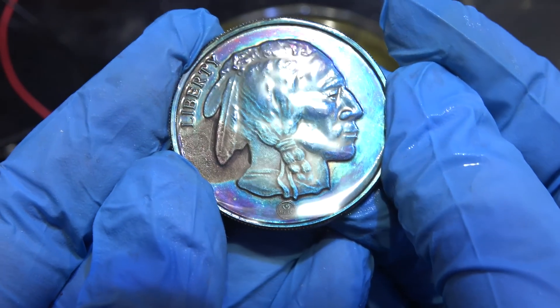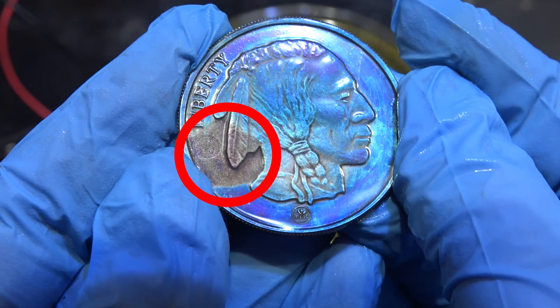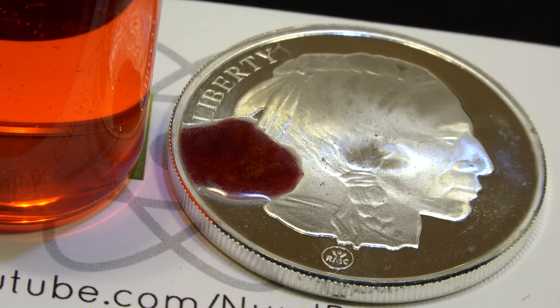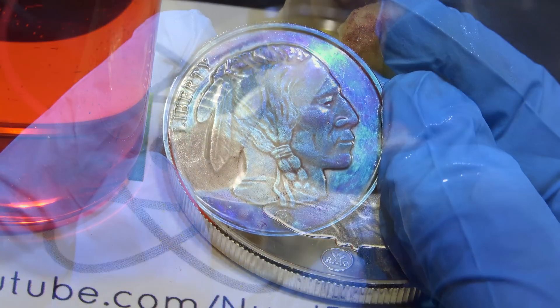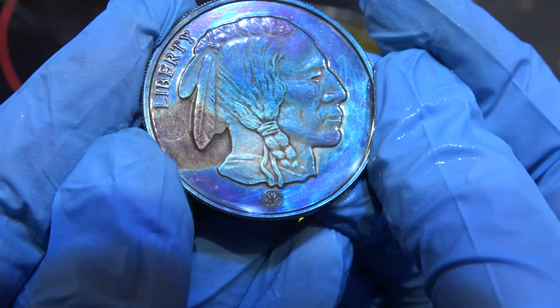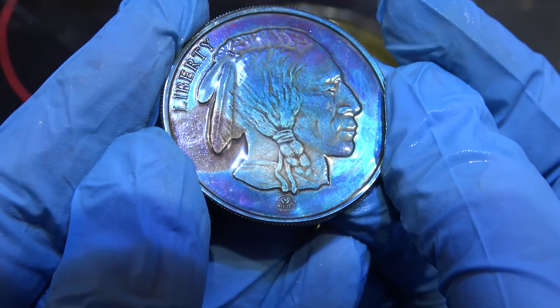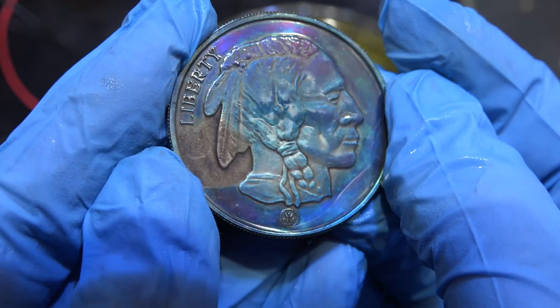A special note about this particular coin: you're probably wondering what's with this splotch that never seems to change. This coin was the same one I used for silver testing with that acid dichromate solution in a previous video. The acid etched the coin so badly that it's been deeply damaged. That splotch is a sandpaper-like surface and while it is being tarnished as usual, it's so rough that we can't see any difference. That's why you don't run silver testing on visible or important parts of a silver item — the damage is extremely unsightly.